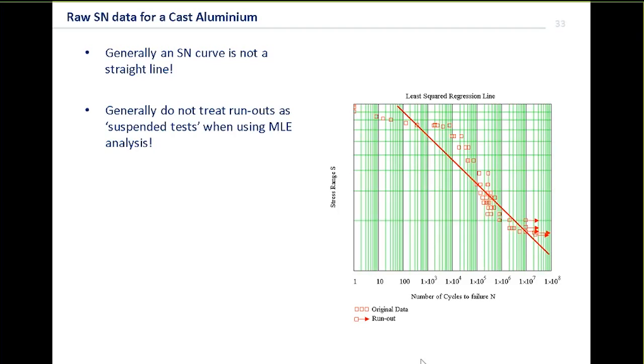So what that means is normally in a reliability test, if the test is suspended because you've hit the run-out limit, then you can still do some nice statistical trickery using probability to include those results in your analysis. But with SN, you can't do that. And that's simply because it's a different failure mode when you get into those post-endurance. So you can't imply that the same statistical distribution was present from the other tests. So that's just a little word of caution for you there. Don't treat these as suspended tests in fatigue, because very often run-outs are a different physical failure mechanism.